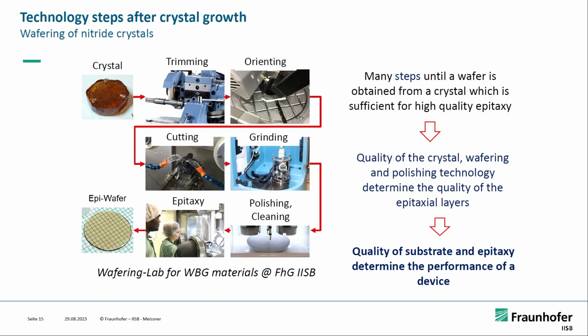There is no time to go into wafering in depth, it's a broad issue, but here you see what wafering means. You have a crystal, you have to trim the crystal because you need a round wafer, but crystals don't necessarily grow round - they grow in whatever shape they want. So you have an oddly shaped crystal, which is hexagonal, then you trim it round, then you need a crystal orientation because the wafer has a defined orientation to the surface. Then you cut it into slices, grind it, clean it, polish it, and then you try it out.